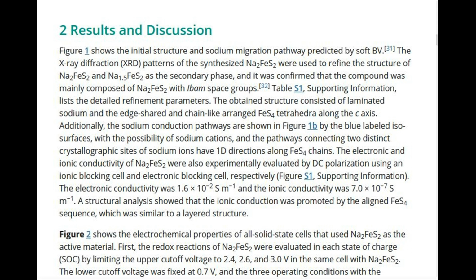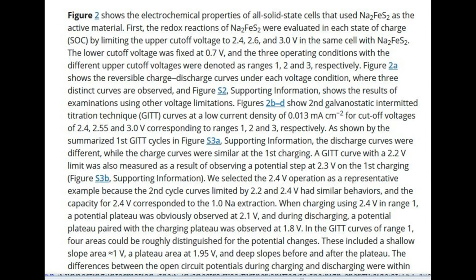First, the redox reactions of Na2FeS2 were evaluated in each state of charge, SOC, by limiting the upper cutoff voltage to 2.4, 2.6, and 3.0 V in the same cell with Na2FeS2. The lower cutoff voltage was fixed at 0.7 V, and the three operating conditions with the different upper cutoff voltages were denoted as ranges 1, 2 and 3, respectively. Figure 2a shows the reversible charge-discharge curves under each voltage condition, where three distinct curves are observed, and Figure S2, Supporting Information, shows the results of examinations using other voltage limitations.